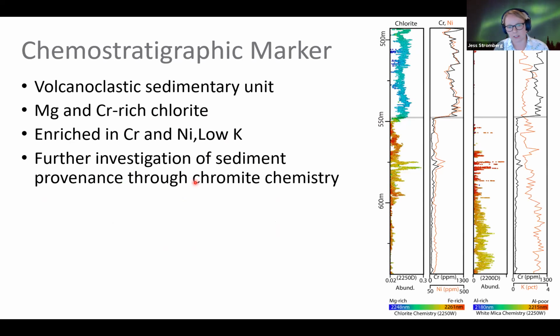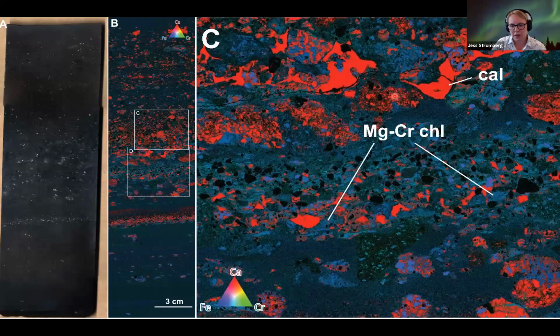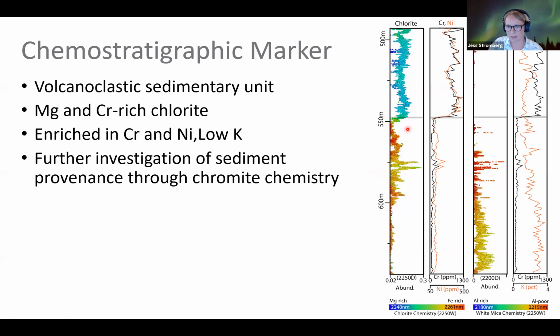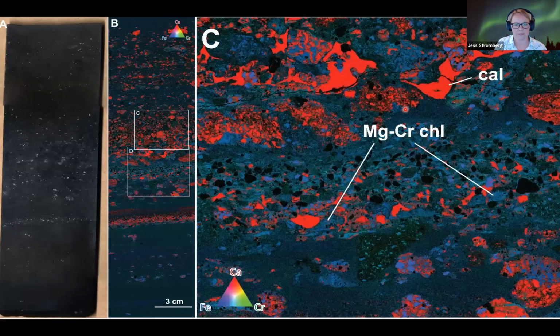And if you look at that in closer detail, in the chemistry, it's actually really nickel and chromium rich as well. And when you go a little bit further, looking at that nickel and chromium enrichment using the XRF mapping, we actually have magnesium chromium chlorites, which is quite interesting. And so this section is not just chromite bits, it's actually chromium in the chlorite. And so that's interesting both as a stratigraphic marker, but also in the context of provenance. That's clearly something kind of ultramafic-y coming in there. And so we're looking at chromite chemistry to investigate that further.